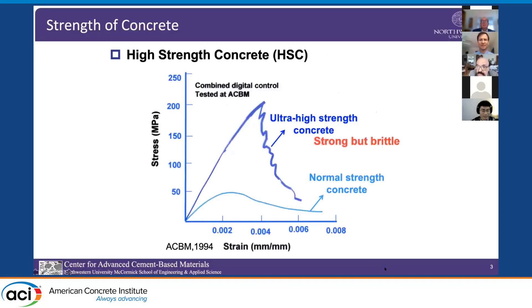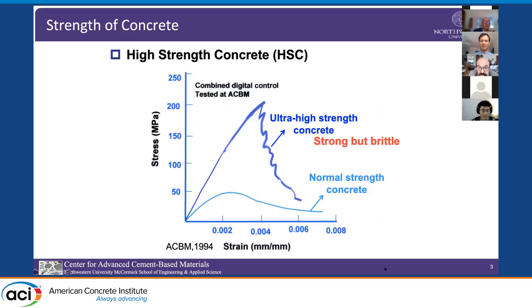I have shown here the stress-strain curve in compression of UHPC. Interestingly, this was done in 1994 and the cylinders for this test were sent to my laboratory from Denmark. As many of you know, Aalborg Cement was one of the first to use so-called ultra-high strength concrete. Notice that we were able to obtain stable post-peak response even with a compressive strength of 200 MPa, but the post-peak is almost vertical.